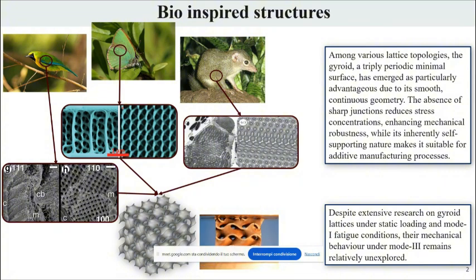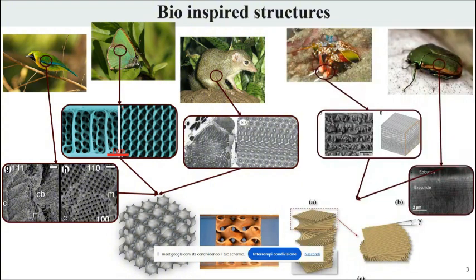And despite there is quite a huge literature about compression, tension, and looking at the fatigue field, the mode 1, there is not a huge literature about pure torsion and mode 3. And talking about pure torsion, I would like to introduce you the Bouligand structure that is interesting under torsion. It's basically a layered structure in which each layer is rotated with respect to the previous one of an angle. And what we thought is, why don't we combine these two kinds of structures, so gyroids and Bouligand, in order to investigate the torsional performance and make new design.